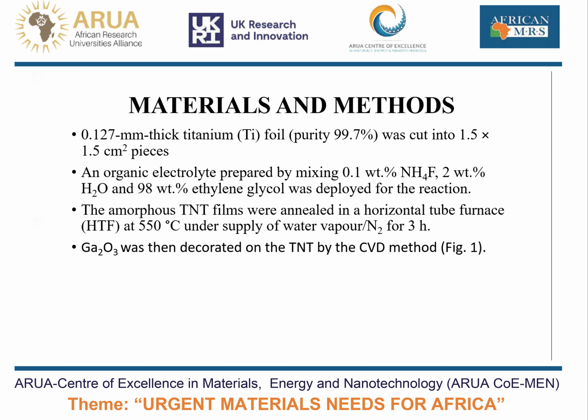An organic electrolyte was prepared by mixing ammonium fluoride, deionized water, and ethylene glycol, and was deployed for the anodization. The obtained titanium nanotube films were amorphous and were therefore annealed in a horizontal tube furnace at 550 degrees Celsius under the supply of nitrogen and water vapor for 3 hours to convert them to crystalline.